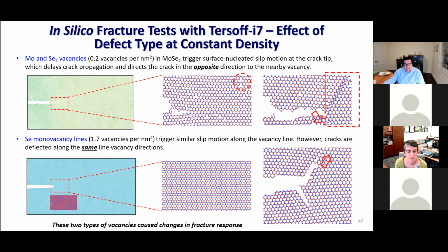There were some studies that look at a sharp crack in graphene, but then you have arrays of vacancies that form 5-7 defects, a type of defect. So imagine that introduces a warping of the lattice, and it's not functionalization, it's the presence of vacancies. We have studied graphene oxide, which has functional groups, this oxygen, and showed that polymers bridging the crack, like I show in this case, could be very conducive to increasing the toughness. So it's a sort of polymer chains bridging the crack and then conferring toughness to the material. So there is where the functionalization could be, and the functionalization, of course, is in relation to how you get hydrogen bonds or other chemical bonds to have the polymer assembled on the 2D material.